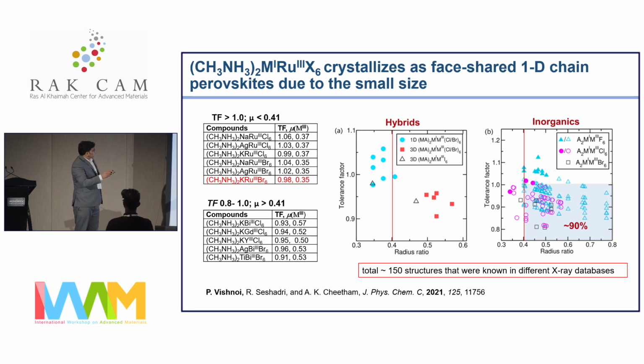And then we looked at the other bunch of compounds where we see the tolerance factor is in the perovskite range, which is the validated range for perovskites. For ABX3, it is well known. It's also known for double perovskite that when one expects to form a perovskite, the tolerance factor should be within 0.8 to 1. And we see it's well within that range. And also the radius ratio is above 0.41.